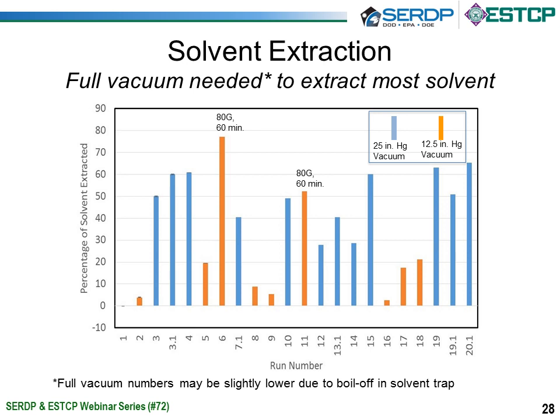For run 6 and run 11, you can see that we did collect a significant amount of solvent using the half vacuum, but these were runs that were run at very high G-forces for very long amounts of time, and we surmised that during these runs, the material heated up, and this heating actually allowed more of the solvent to vaporize off.